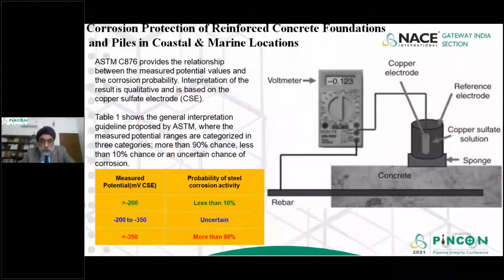Now, how do we check a concrete which is embedded partly in the ground and partly in the air, whether the rebar is corroding or not? So we all understand the science of measuring, in our terminology, pipe to soil potential. The same terminology or the same systems are used for checking what is happening on the rebar without removing the concrete. ASTM C876 provides a relationship between the measured potential values and the corrosion probability.